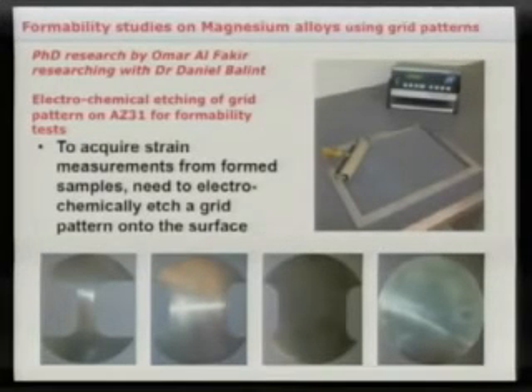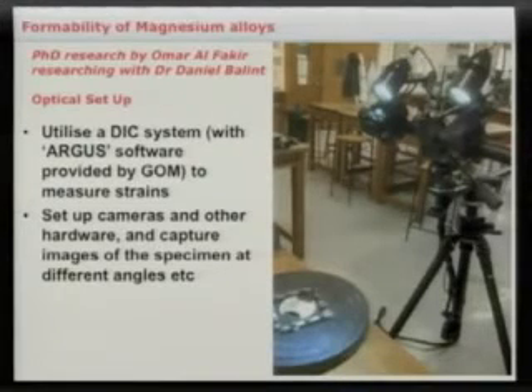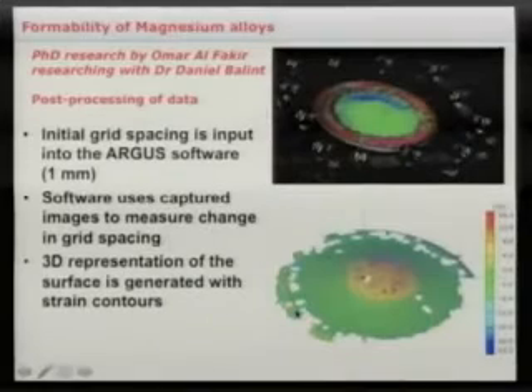The strain visualization technique that is used here is one which Omar has been applying. It's a commercial technique in which a series of markers are put on the component, and then the component is deformed, and you can use the camera system in much the same way as you saw over there. In this case, you put the component, you form it, and you have a series of little calibration plates here which provide sort of references for the cameras. And here you have the camera, the turntable then rotates, and you capture a series of images of this, and you can then build up a three-dimensional picture of what's happened to the component after it's formed.